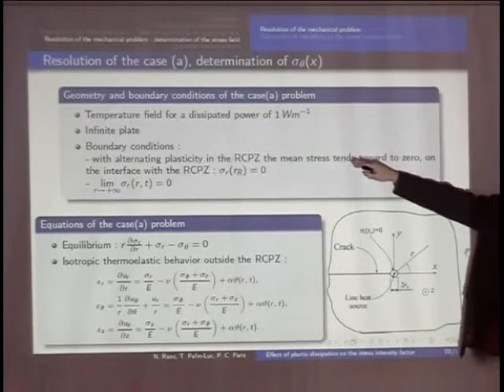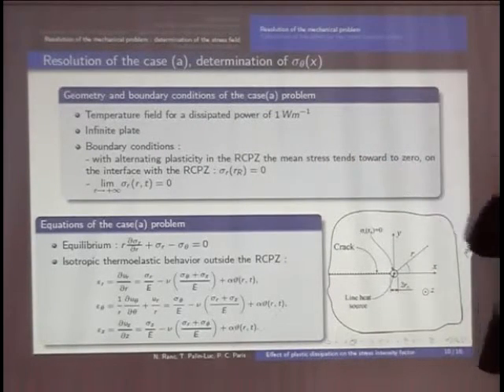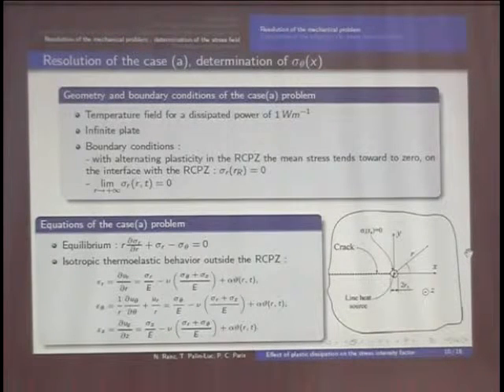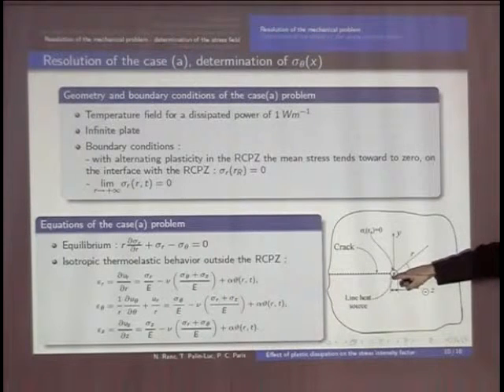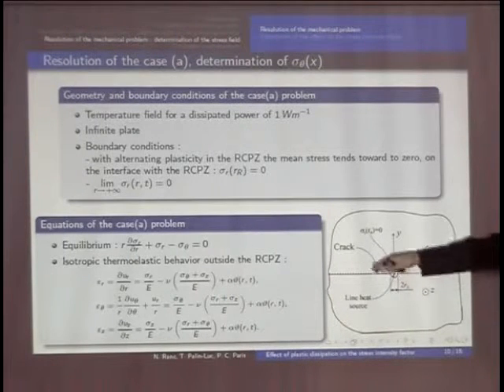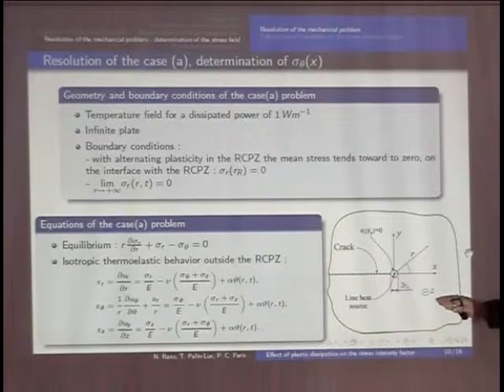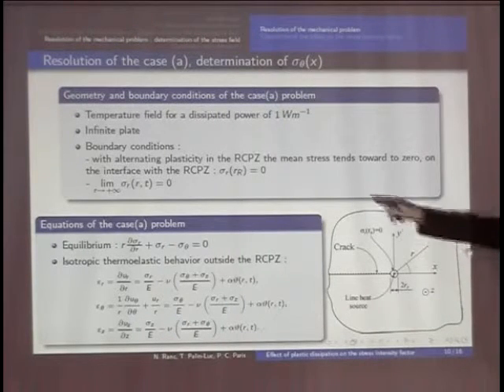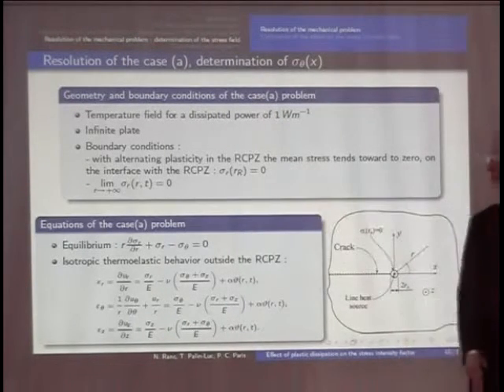And inside the reverse plastic zone, due to the reverse cyclic plasticity, the mean stress goes to 0. So we consider that at the frontier between the reverse cyclic plastic zone and the elastic field of the material, the mean stress is equal to 0. So it's the other important boundary condition.